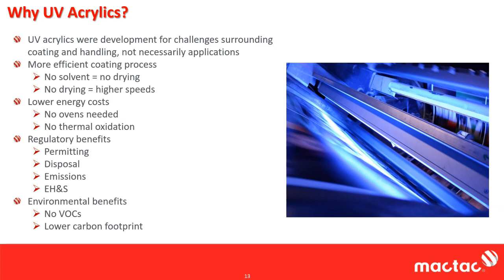And then the environmental benefits, again, no VOCs and a lot lower carbon footprint. And this really goes back to burning the natural gas for the dryers. Our new coater that we built to run the UV acrylics and a lot of the hot melt rubbers, in an entire year, that thing does not consume 1 month's worth of natural gas of one of our old solvent lines fired. So much lower carbon footprint. And that's really why the UV acrylics came about. Again, it wasn't necessarily that the solvent acrylics weren't meeting any certain performance requirement.